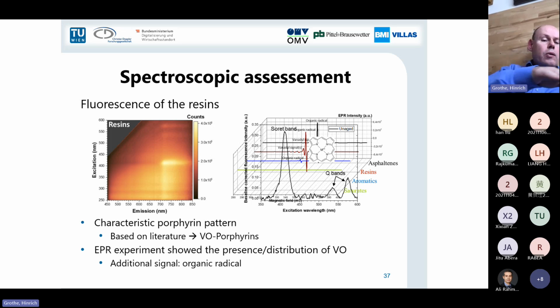And of course, you can then also have not a map, but a normal fluorescence spectrum. And what we have learned here from this kind of fluorescence spectroscopy of the resins is that we have quite an interesting compound inside, which is the porphyrins. And these porphyrins are chelating metal oxides. And a very important metal inside bitumen is vanadium, and vanadium forms vanadium oxide. So the vanadium oxide is complexed in these porphyrins.